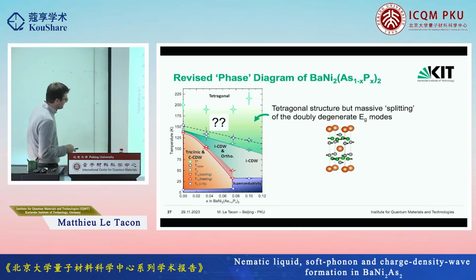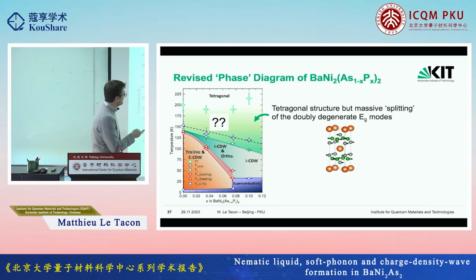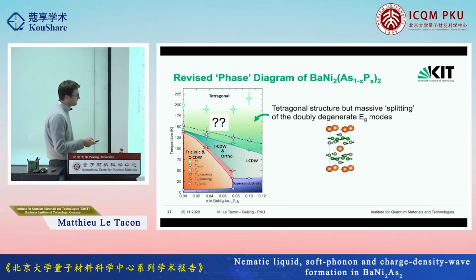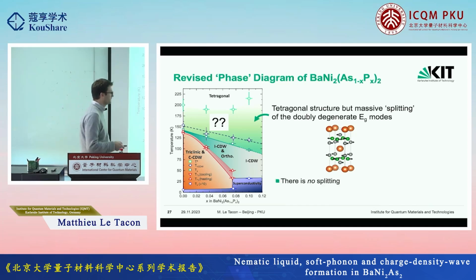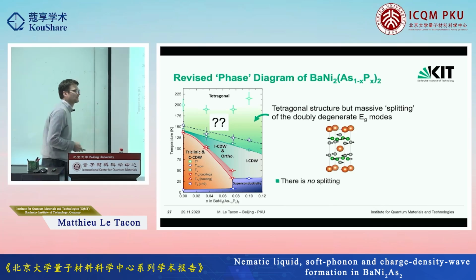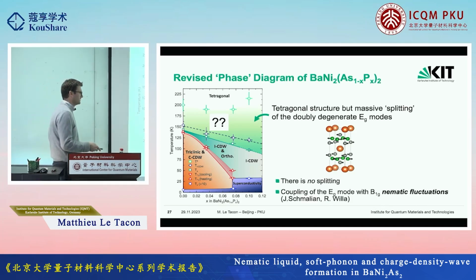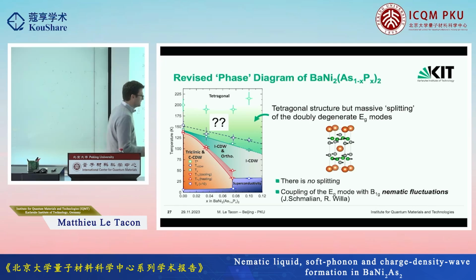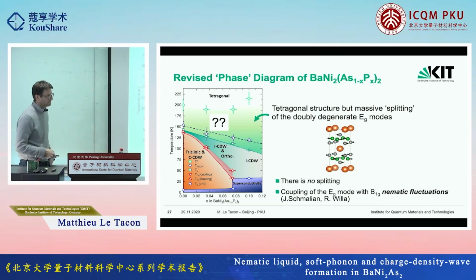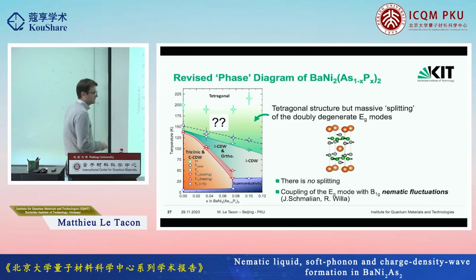So this has been really puzzling us, and that's where Schmalian come in the game. I say, well, I have a tetragonal compound, and I have this splitting of the EG mode. What causes that? And then his answer was very easy. He said, well, there's no splitting. And what you see is actually a coupling, the effect of the coupling of your mode with some nematic fluctuations. So it was a fairly bold statement, but it didn't come out of the blue.